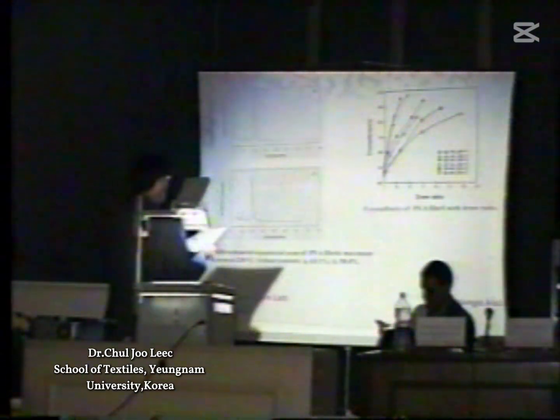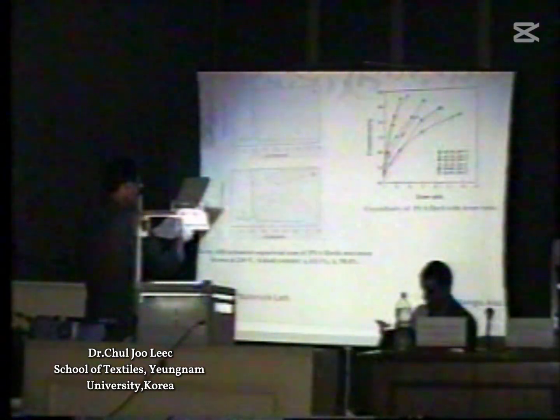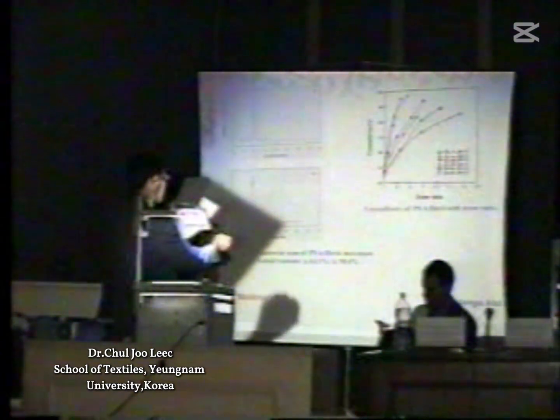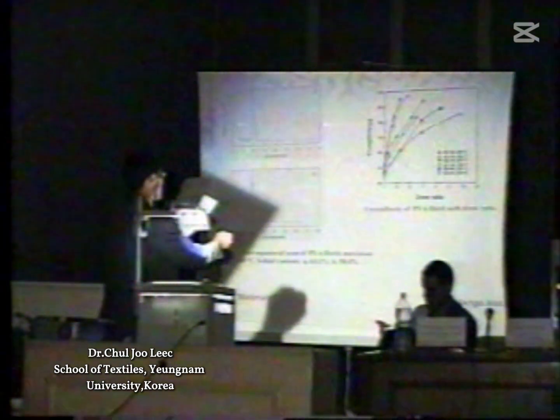This figure shows the effect of syndiotacticity on crystallinity. The crystallinity was increased in accordance with the increase of syndiotactic diad content. As you see, the syndiotactic diad content is right over here. So as the syndiotactic diad content is increased, the crystallinity is increased.